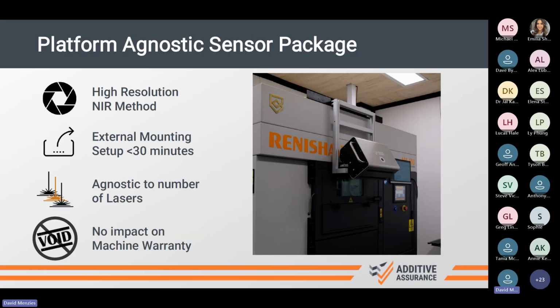So on this image here, that's a Renishaw machine. What we have there is our sensor package. It's looking through that build chamber window that you may be aware of on the front of these machines. We are looking in that near infrared range, so the build chamber windows typically don't have any filtration there, which means that we're able to look through that window. We've got a mounting setup that takes probably less than 30 minutes to get on. There's obviously some calibration that occurs after that.